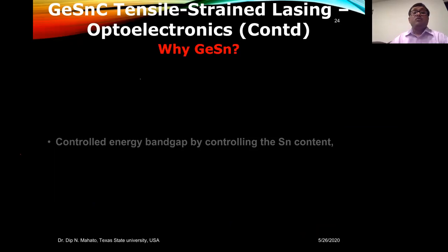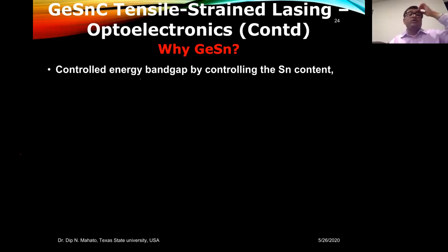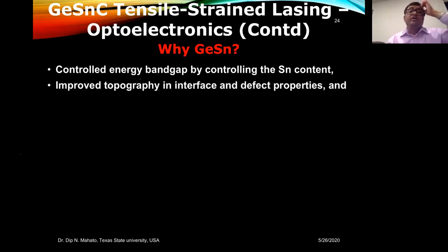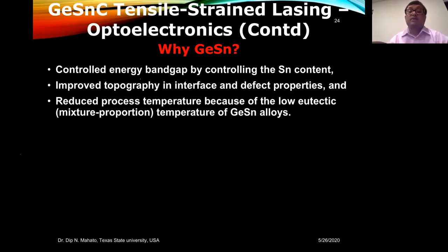But then why tin? Because you have better control of the band gap engineering by controlling the tin content. Also you have smooth, improved topography at the interface between the two layers, and mostly defect-free. And there is reduced process temperature also, because of the low mixture proportion temperature of germanium tin alloys. These are the reasons you choose germanium tin.